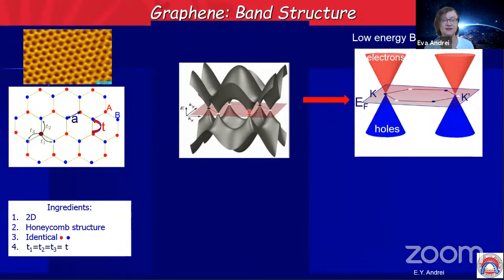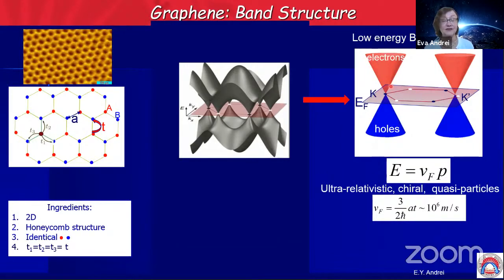The points here where the band structure closes are called Dirac points. And the band structure here consists of 2 cones, 2 what we call Dirac cones. In the red part here, we have electrons. In the blue part here, we have holes. And the hexagonal Brillouin zone is here. K and K prime are inequivalent points in the Brillouin zone. And the energy-momentum relation, unlike for the massive free particles that I showed you before, is not quadratic in momentum, but it's linear in momentum. So this is in a sense exactly like the dispersion of photons or neutrinos. And as a result, we call these ultra-relativistic particles.